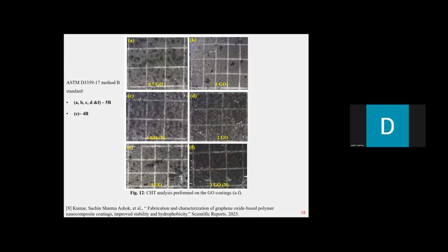And we can see that A to F, which represents the 0.5 up to 3 weight percentage GO, from here we can see that A, B, C, D, and F exhibited a 5B rating. That means there was no detachment of any flakes. The surface was smooth. The coatings were intact. There were no cracks.